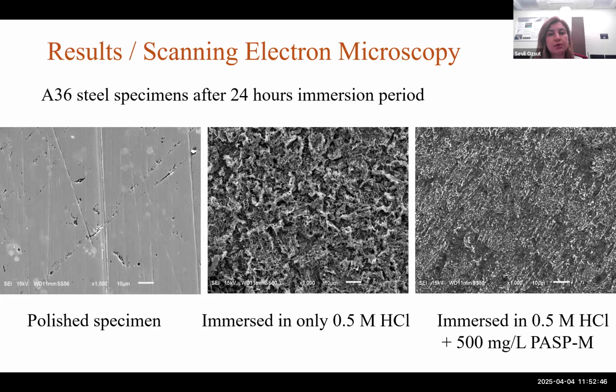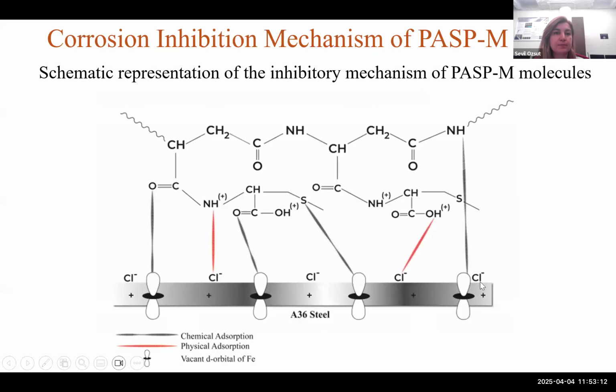Again, we have some corrosive species, some products, but this time we get a smoother surface compared to the hydrochloric acid only case, which shows that the inhibitor is adsorbed on the surface, decreasing the corrosion rate and giving higher inhibition efficiency for that metal.